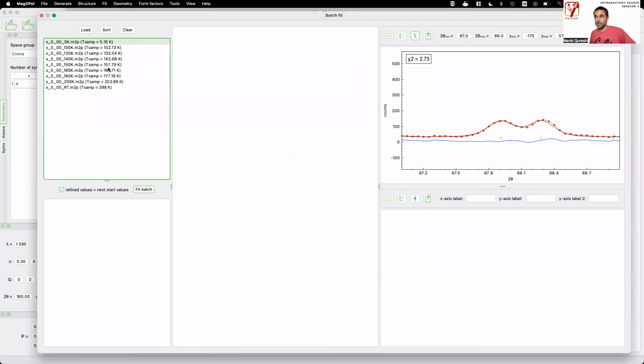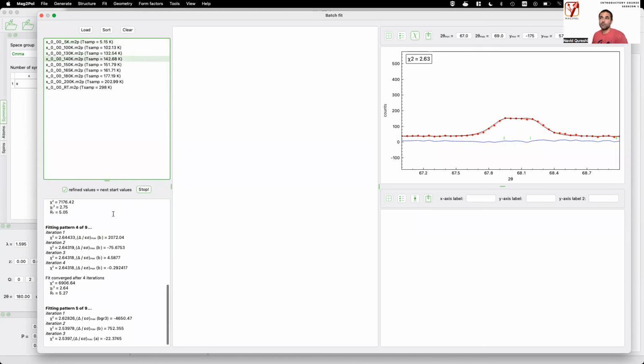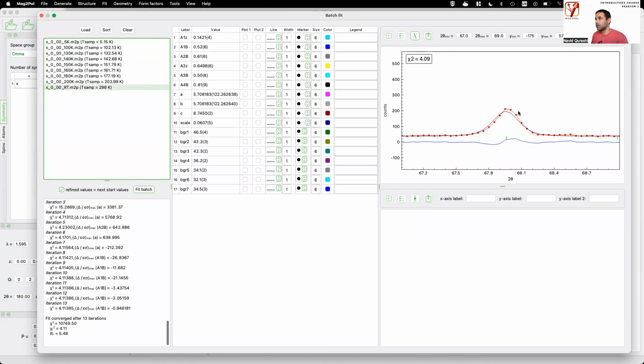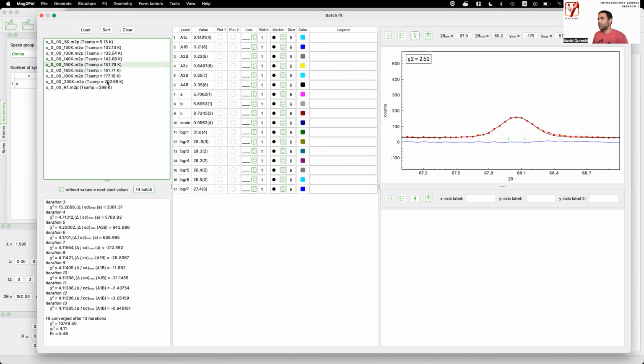You see now the temperature which has been loaded or read from the metadata. And now I can do the fit batch using this option where the refined value of one fit will be the starting values of the next one. And if your jumps in temperature in that case are not too big, well, then actually that should work quite well. So I click fit batch and it will now fit all the patterns, and you can see how it changes here already in that window. You can go back and see the fitted line and the observed pattern. You can see here how your refined parameters change, and they're already given with the standard deviation.